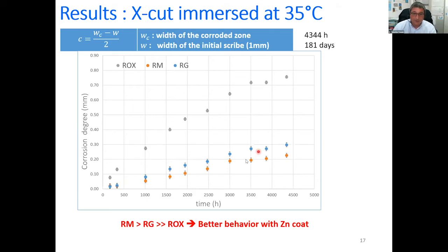And for RM and RG, it seems that RM is better than RG, but we have lower values of the corrosion degree. So the conclusion here is that, of course, the system is better with a zinc coat, so a thermal spray coat or the galvanized coat.